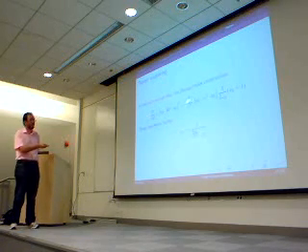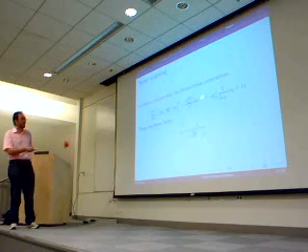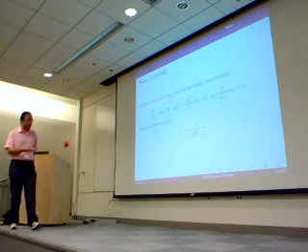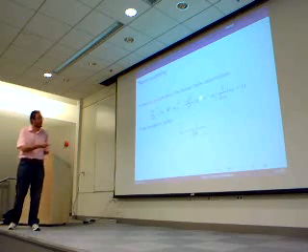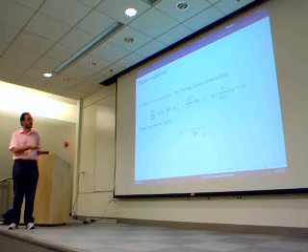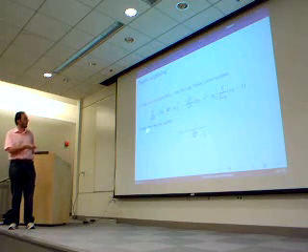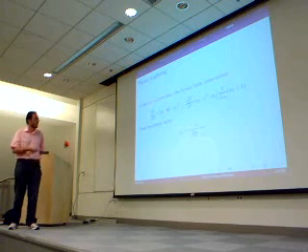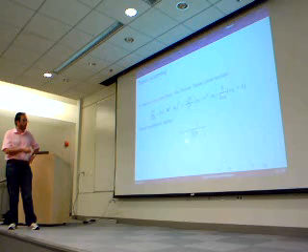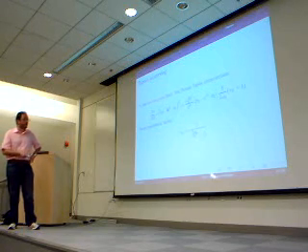V, in this case, is the total volume of the sample. Then alpha K is the proper Raman tensor for the K vibrational mode. Here is the frequency of the mode. And then we have a boson population factor for phonons at the frequency omega.